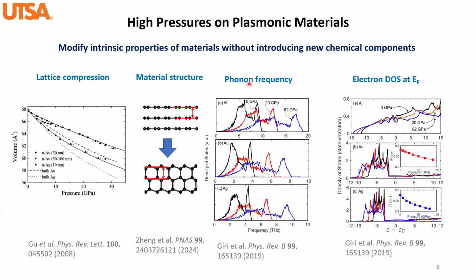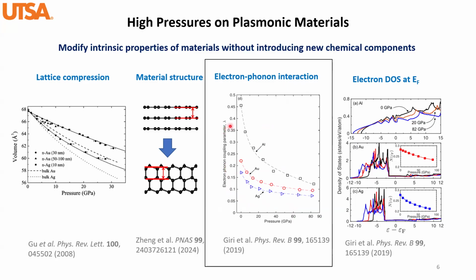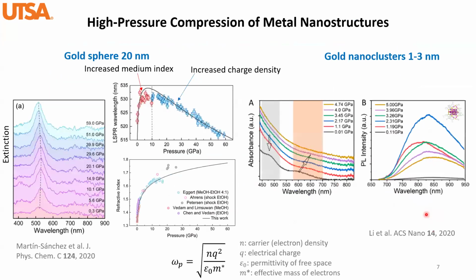In terms of phonon frequency, gold, silver, and aluminum are all plasmonic materials, and we can see that the phonon vibration shifts to a higher frequency. As a result, the electron-phonon coupling drops significantly under high pressures. And as we mentioned, electron-phonon coupling is one of the major loss mechanisms in surface plasmons. And when it comes to the electron density of states at the Fermi energy level, we have been seeing a constant drop of the DOS as well under high pressures for gold and silver. Okay, so let's take a look at what happened to metal nanostructures under high pressures.